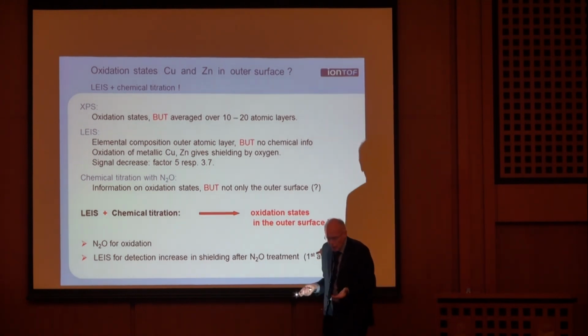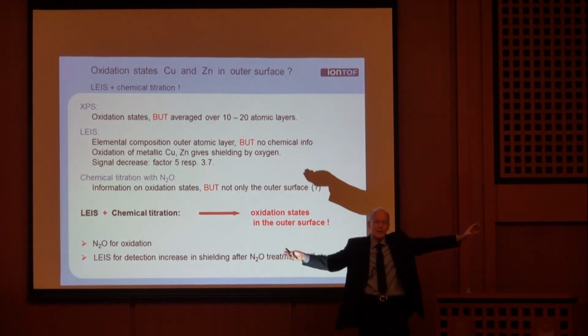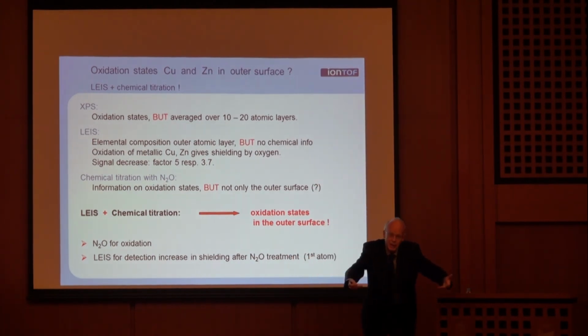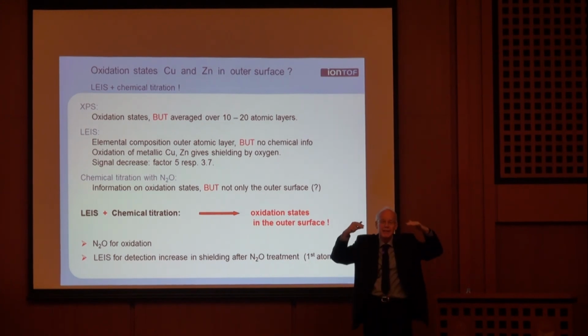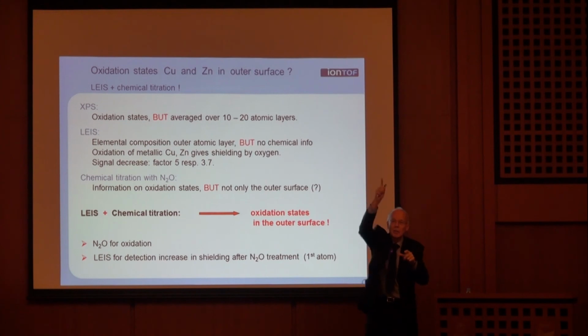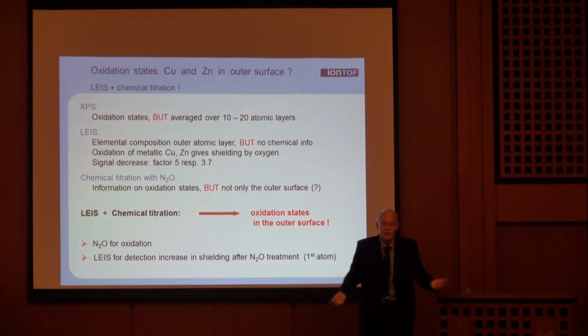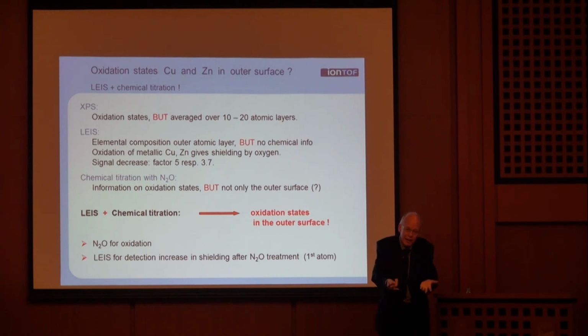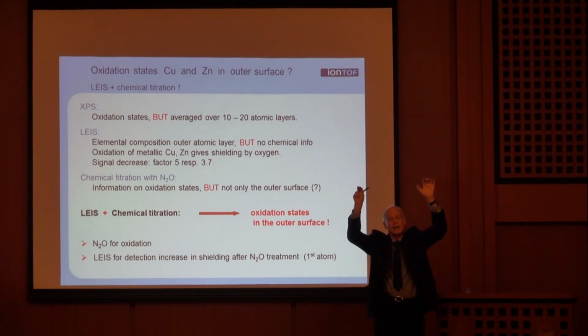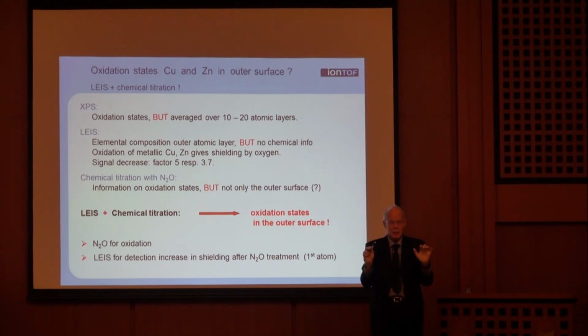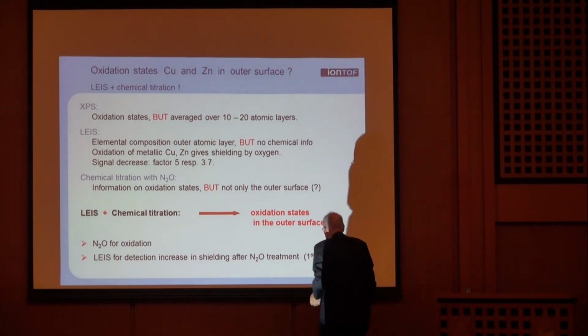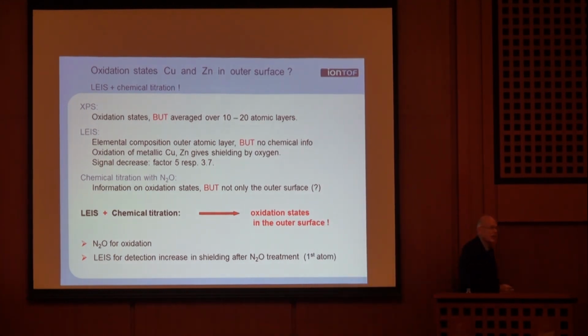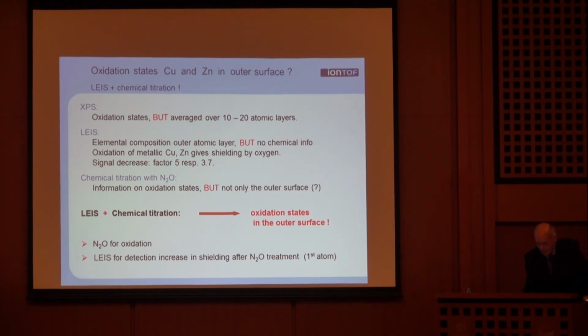So, all I have to do, if I have a complicated catalyst, is measure after preparation, after activating the catalyst. I see a copper peak and perhaps other things if there are. And then I oxidize and I see how far the signal of the copper and the zinc decrease. If they stay the same, they were already in the highest oxidation state. If they get lower, apparently they were more in a lower oxidation state. And in that way, you can determine the oxidation state of this catalyst.